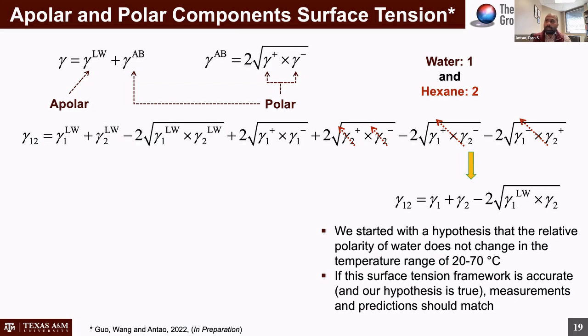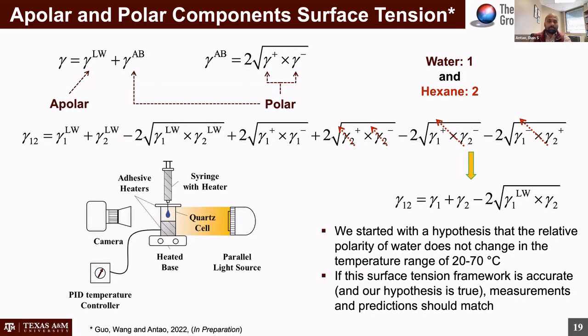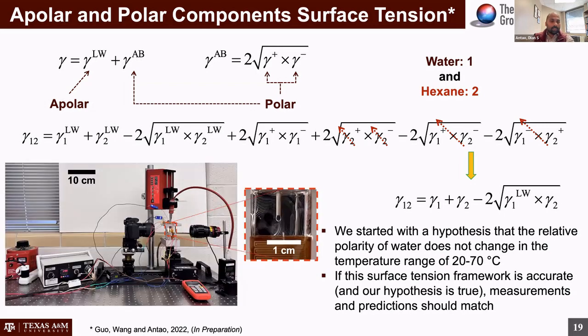And to do these experiments, my student put together this test setup to do very controlled measurements of surface tension and interfacial tension using the pendant droplet method. I've got to give her a shout out. She really has done some of the cleanest measurements I have seen for surface tension and interfacial tension over a fairly wide temperature range. Again, that's maybe my bias because she's my student, but I think she's done some really great work. This is what the setup looks like. And let's take a look at some of the data.